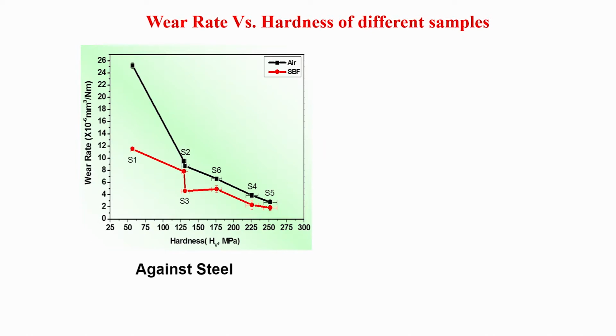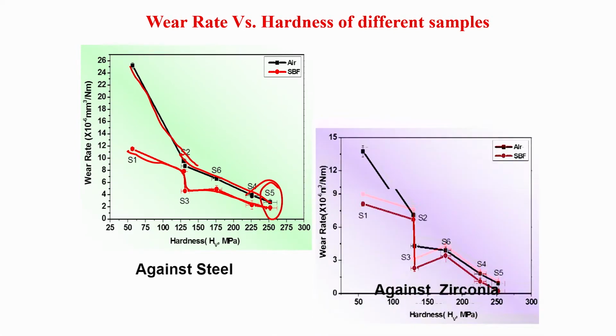When steel is used as a counter body, going from S1 to S5, you see a reduction in the ambient conditions. There is also a reduction in the simulated body fluid, but by far that reduction in ambient is much more significant compared to reduction in simulated body fluid. This means that in simulated body fluid anyway wear rate is lower, but still we have observed, particularly in case of S5, that much lower wear rate can be measured against steel.